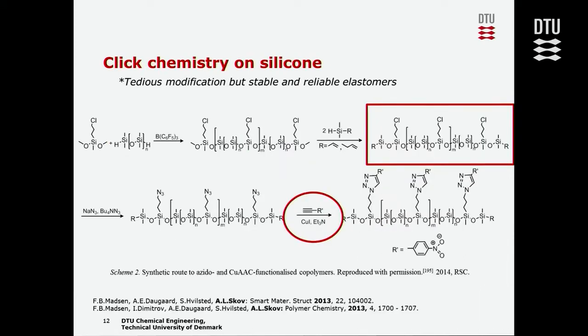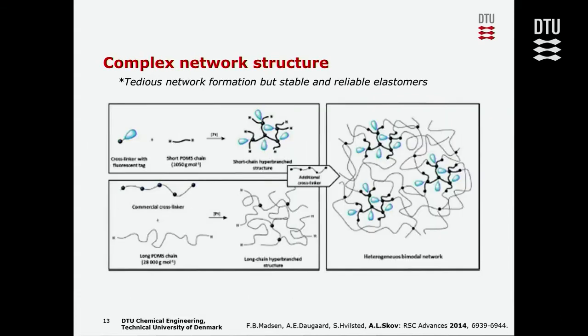Oh, I should say the click chemistry, at some point we simply thought it was too tedious, but as I'll come back to later, there are actually very good things about having the full control over the chemistry and thereby also of the elastomer. So it may be worthwhile using this approach. Then we also said instead of improving the dielectric permittivity, we look at the Young's modulus as the sole optimization factor. And we played around with making bimodal networks.